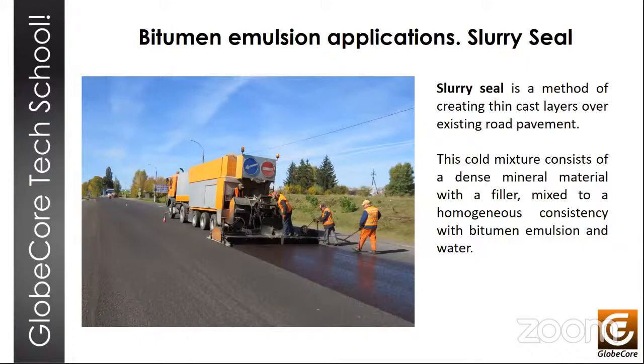After the drying time, the surface becomes impermeable to water. The coefficient of traction is improved, so the old coat is protected from water, oxidation, and further deterioration. The thickness of the slurry seal coat is 1 to 1.5 times the size of the stone grain, something like up to 8 millimeters. This mixture uses material homogeneous in terms of particle size distribution.